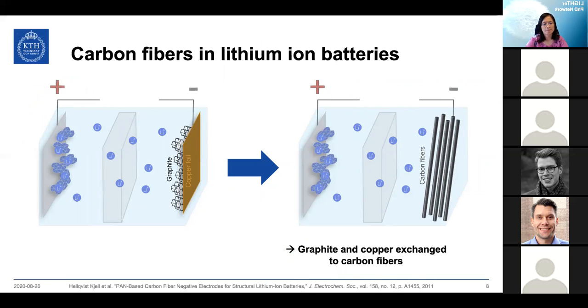It has also been shown that carbon fibers can do the work as the negative electrode in a lithium-ion battery. The carbon fibers can both store lithium ions as well as being electrically conductive, meaning that the copper foil and the graphite powder can be replaced with carbon fibers. However, this is all still in a liquid electrolyte, meaning that the carbon fibers do not have the ability to carry load.